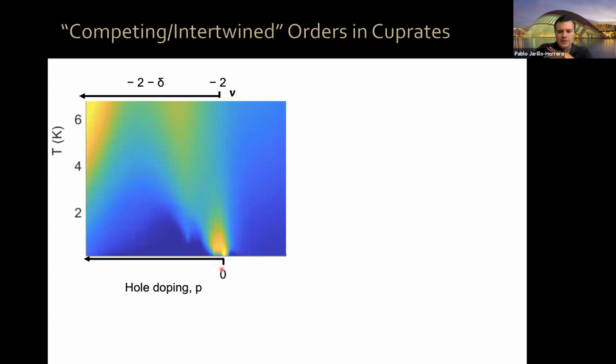So remember, from the point of view of doping, this is the correlated insulator state for 2 holes per moiré unit cell, which in terms of extra doping corresponds to 0, filling factor -2. And in this direction, we add more holes to the system. And as you can see, we have a superconducting dome, which clearly shows 2 bumps. And the depression here in Tc seems to be related to this resistance ridge, which we observed at higher temperature.